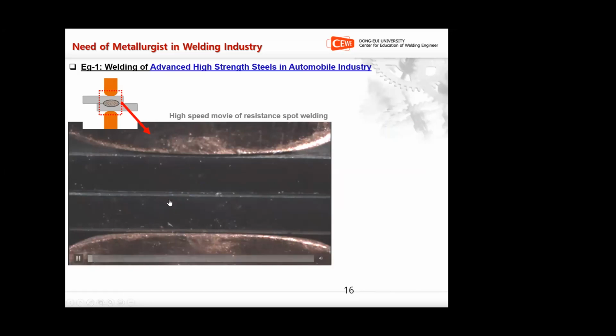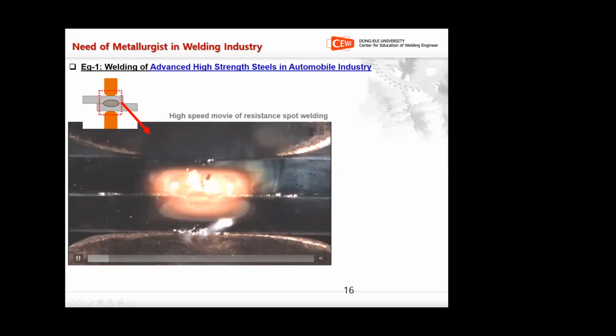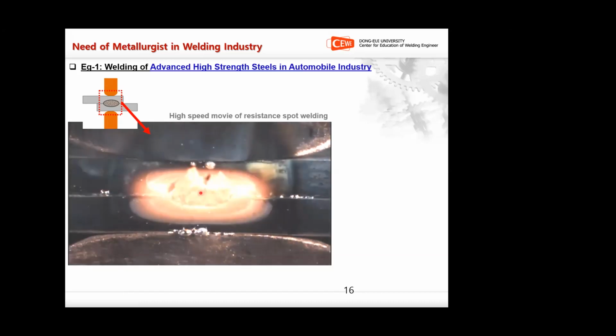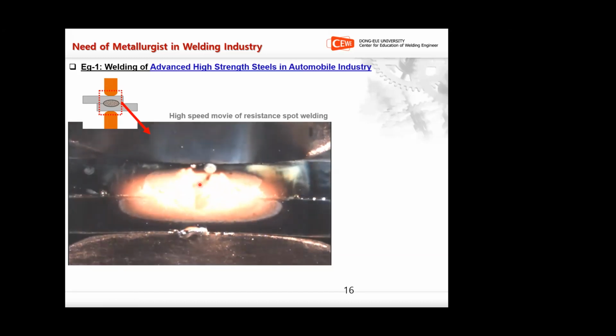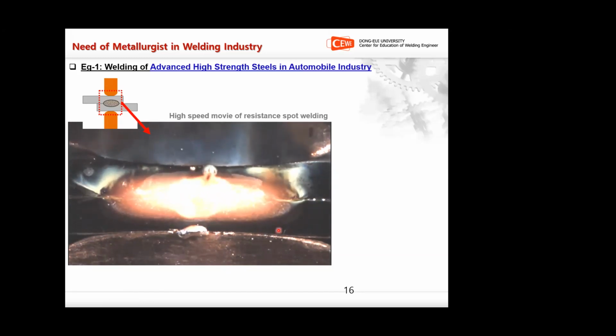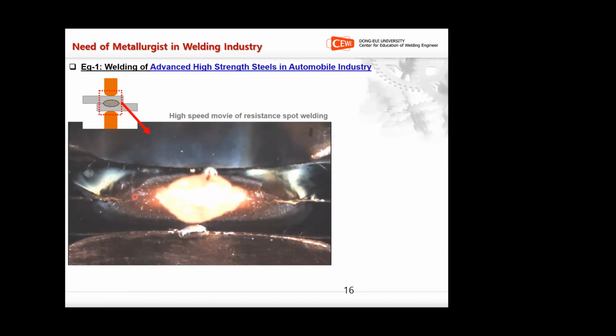So let's see what is happening. This is a high-speed camera movie. Current is passed, and you will see the melting of the coating. Here the coating is melted, and here the steel has been melted. At the same time, if you look carefully, you will see a lot of spark formation. Here, here, here, and after some time here also. So these electrode-sheet interfaces experience a lot of spark formation. These are called sparks, and almost all the interfaces have sparks.